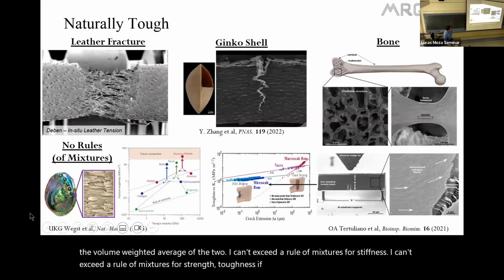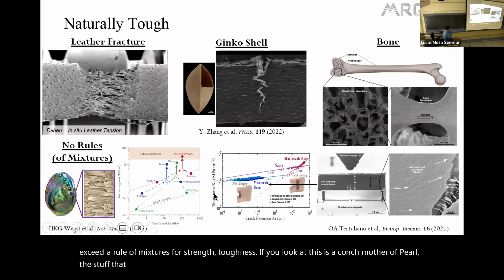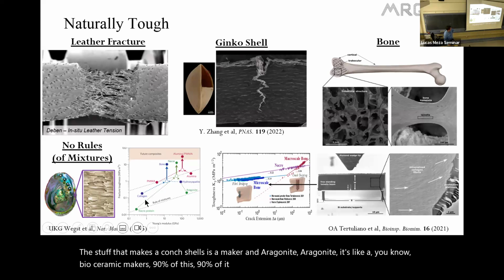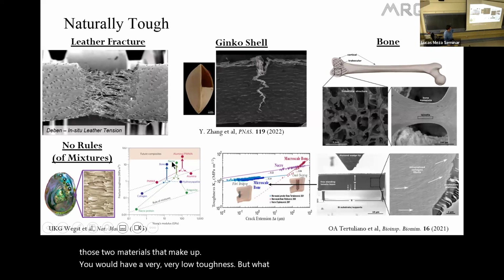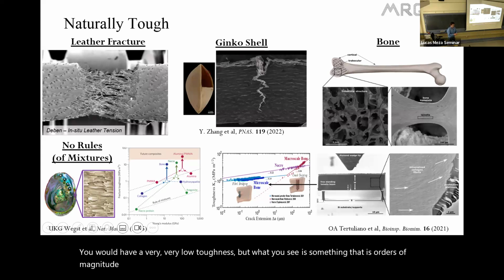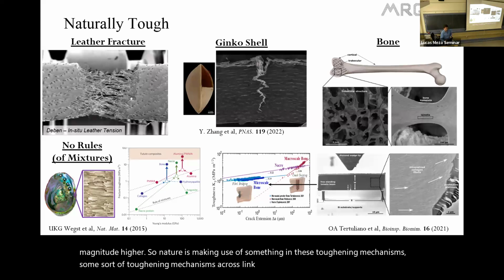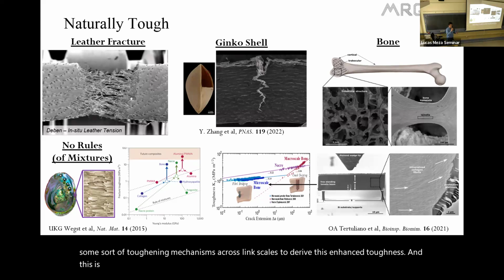Toughness, if you look at, this is a conch mother of pearl. The stuff that makes up conch shells is nacre and aragonite. Aragonite, it's a bioceramic. Nacre is 90% of this, 90% of it is this bioceramic. If you took a rule of mixtures between those two materials that make up nacre, you would have a very, very low toughness. But what you see is something that is orders of magnitude higher. So nature is making use of some sort of toughening mechanisms across length scales to derive this enhanced toughness. And this is really what drew us in.